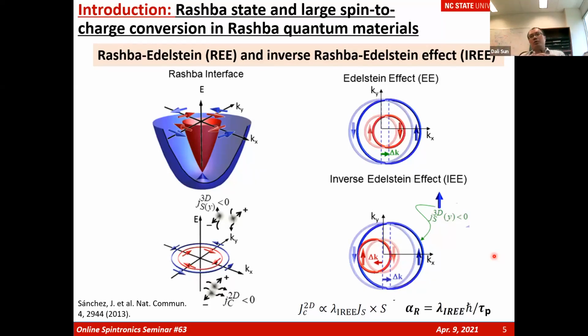They can also be used as very efficient spin detectors and spin current generators or emitters for multiple spintronics applications. If we consider the conversion, the two-dimensional charge current induced by the Rashba effect can be described by a simple equation: it is induced by the three-dimensional spin diffusion current, cross product with the spin orientation. This efficiency is defined by a length called the lambda IEE coherent length, for the Rashba-Edelstein effect. And by estimating the lambda IEE length, we can estimate the Rashba parameters in these typical materials.